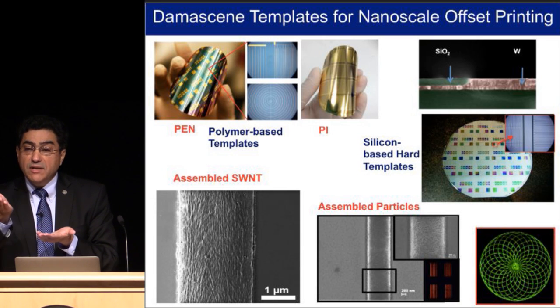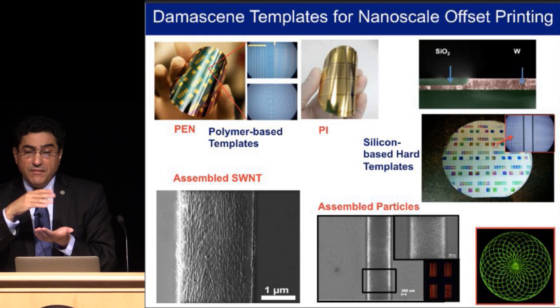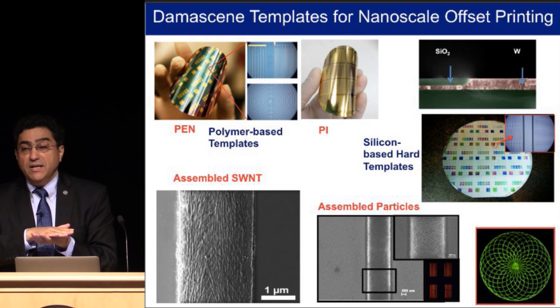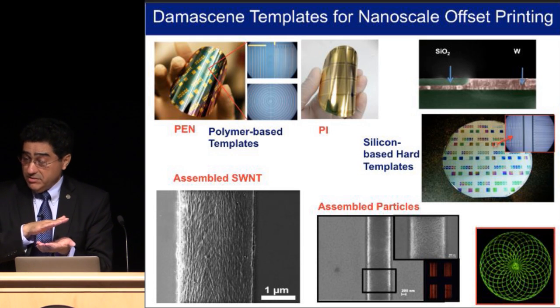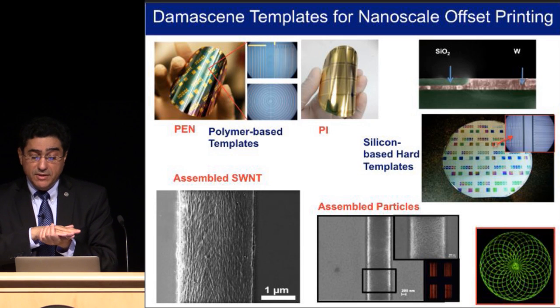Now, when you print, you have a gravure roller, or you have a plate, and the plate is hard, and you have paper which is a little bit softer. You can push it down. So when you print, you have to have full contact. So when you have two hard surfaces, you cannot have full contact. It's almost impossible. So to print on a soft surface like polymer, for example, we use a hard template. But to print on a hard surface like silicon or other surfaces or metal, you have to have a softer plastic-based template. So this is the plastic-based template.